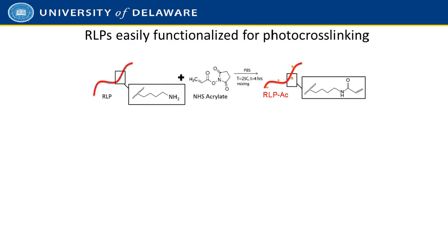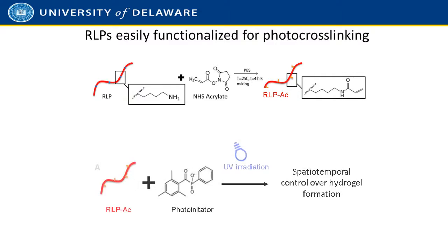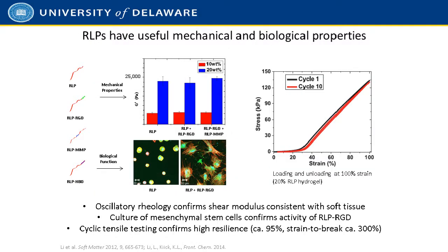Because we've engineered the sequences to carry chemically reactive groups, in this case amine groups, the NH2s, we can functionalize the RLPs with reactive groups, shown here these double bonds on the far end of the linker after it's connected to the RLP, that allows these materials to be photo cross-linked. So we can make these photo cross-linkable materials. They're functionalized with acrylate groups, so the same sorts of monomers that are in the acrylate and methacrylate polymers that Varo introduced earlier in the talk, with the addition of a photo initiator and then irradiation with UV light. We can make hydrogels that have spatio-temporal control.